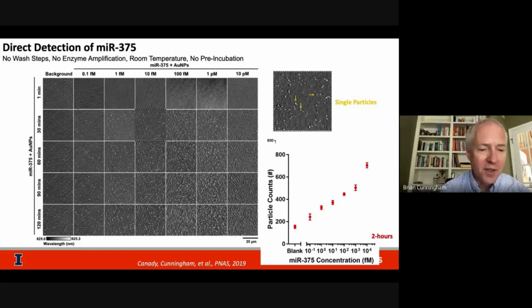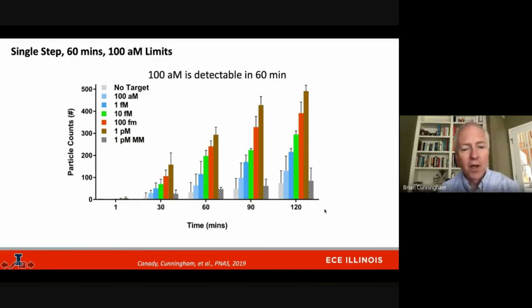So going from the lowest concentration of 0.1 femtomolar and then going up by orders of magnitude, we can see how, as we go from low numbers to higher numbers of molecules, after just a 2-hour incubation happening at room temperature with no stirring at all, we can cover 5 orders of magnitude dynamic range and have a very quantified outcome. Here I just show in bar graph format the same data that I just showed you in the images.